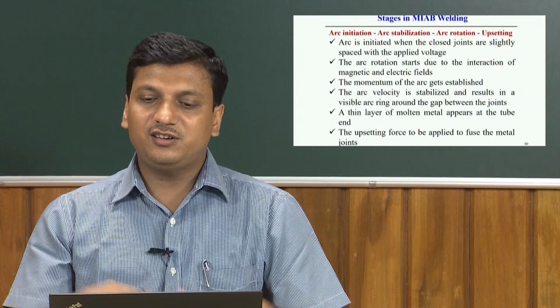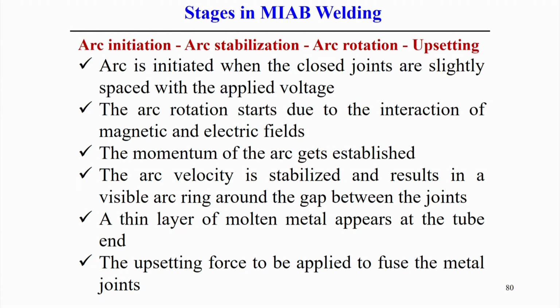So, what are the stages of the magnetic impelled arc butt welding process? There are four basic steps. First is the initiation of the arc, then stabilization of the arc, arc rotation, and finally, upsetting. That means mechanical forging is required in this case also. So, these are the four basic steps.